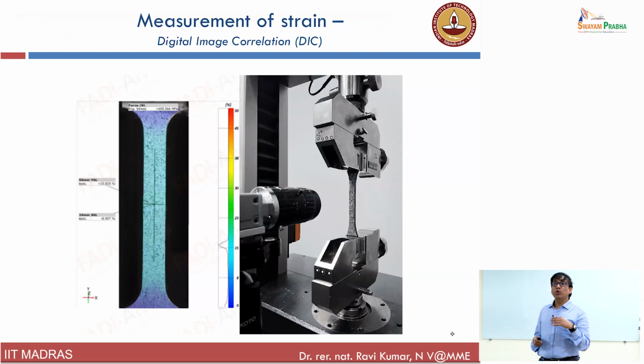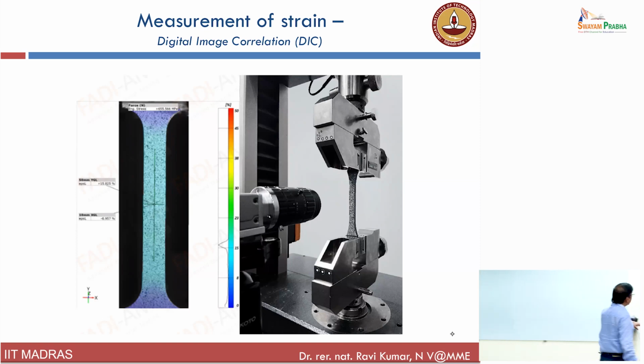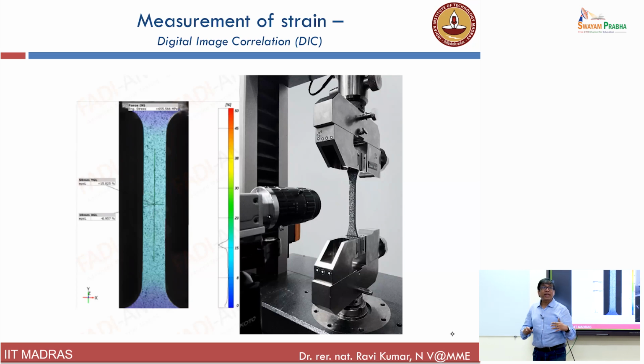And in modern times, people are also using digital image correlation technique. I am not sure how many of you have heard. So basically, you make a speckle pattern. You take this sample, whatever it may be, ceramic, metal, whatever. Then you apply a white paint and then put a black dot speckle pattern, a random set of patterns, and then use high resolution, high speed cameras to capture the relative displacement of all these points so that you get a complete strain contour. So unlike strain gauges and unlike laser extensometer, when you use digital image correlation technique, you get a complete strain contour map. You get complete information about the strain over that entire surface.